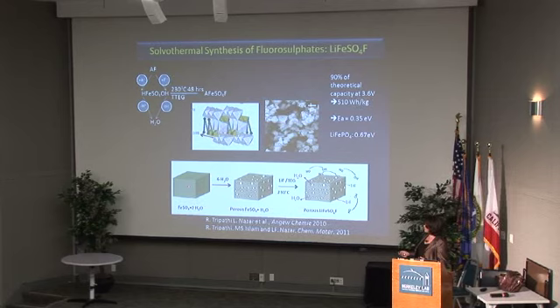So we just take iron sulfate, and this is the heptahydrate. We convert it to a porous material by blowing off some of the water, and then this material can be seen as an HOH. So the H is exchanged for lithium, and the OH is exchanged for fluorine, and we end up with LiFeSO4F. And that little diagram is shown here. So this produces a slightly porous material that allows really good electrolyte access, which allows us to achieve fairly good energy densities at reasonable rate capabilities for the material.